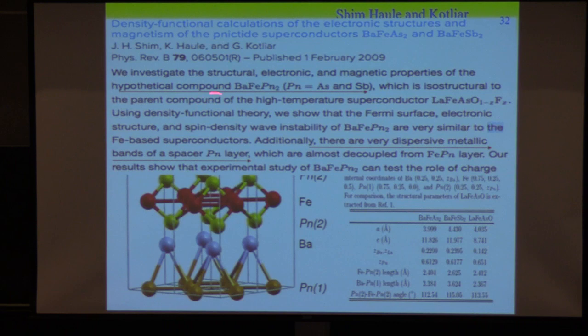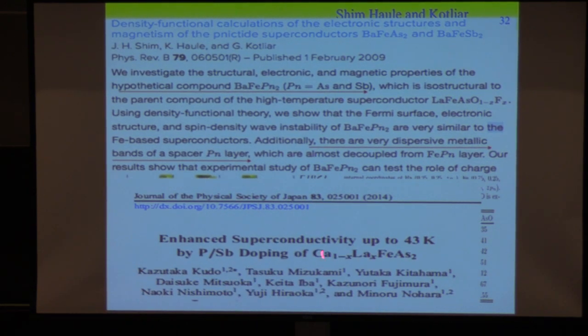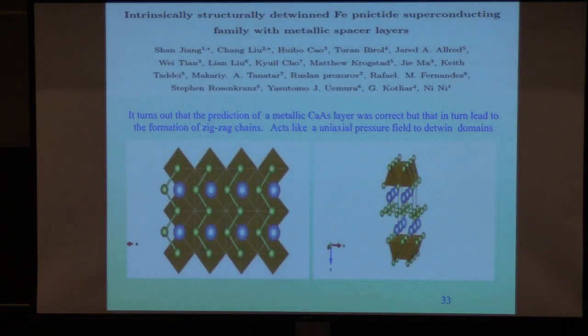But I don't like the term hypothetical compound because it suggests that it does not exist. And a few years later, in fact, the compound did exist in that family, the 112 family. It's a 43 Kelvin superconductor. And now I was talking to Andrew about the DMREF. A chemist at UCLA has been studying this material more precisely. The theory was not perfect in the sense that there was a slight distortion of this structure. So it was not a perfect square net in the metallic layer. It tends to form zigzag chains, so it does distort.